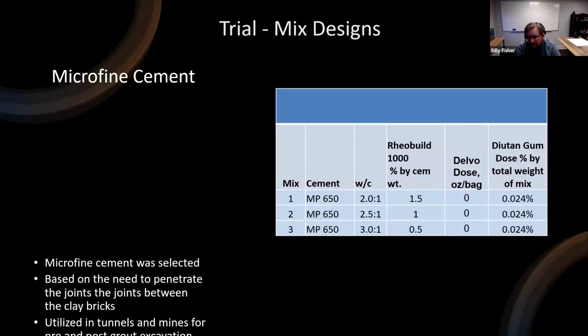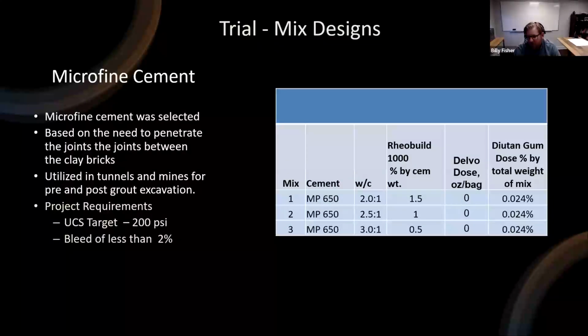We were targeting like 200 psi for the grout. We figured we just needed to be strong enough to lock all the material together, but also weak enough where we could tunnel back through this. And then we wanted to limit the bleed to less than 2%.